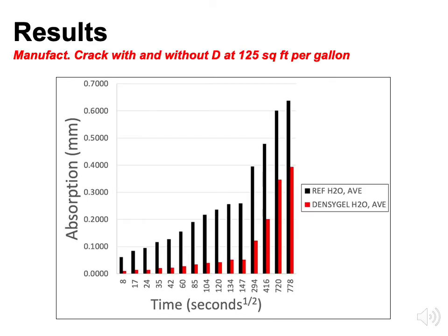The results. So what we did is set up a series of tests using this ASTM C1585, and we pre-treated the concrete crack first with potable water, and we applied the Density gel at 125 square feet per gallon, and then ran the test 12 hours later. And of course, we had our references, and with the reference, we followed the same standard operating procedure that we were going to use in the field, as well as on this other Density gel sample. We wanted to keep all the samples the same method. And what we found after 7 days is that the Density gel bridged that concrete crack, rejuvenated it so that it absorbed less water than the reference, or the concrete crack without the Density gel.